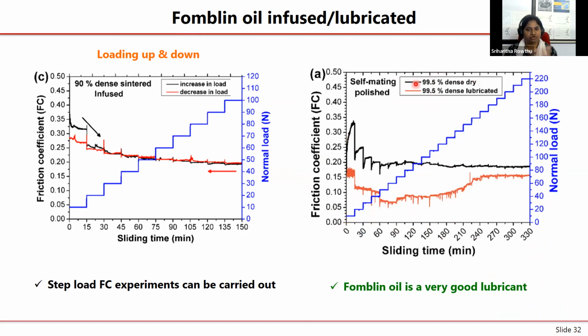Okay, so that's what we have been always doing, the step load experiments. Here I'm going to first of all show that if you have a fully dense alumina specimen, but in the dry condition, there is no lubricant at all, then the friction coefficient is changing from 0.3 and almost goes to a steady friction coefficient of around 0.18 or 0.2. But now if you add a lubricant on top of the surface, then the friction coefficient can decrease, certainly.